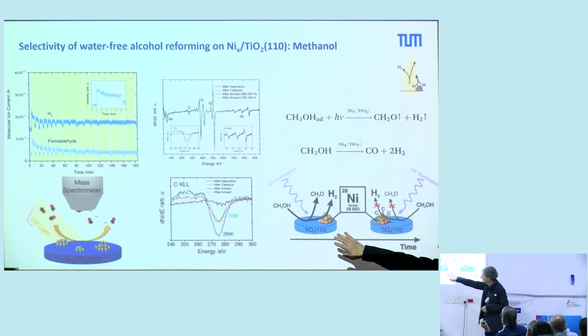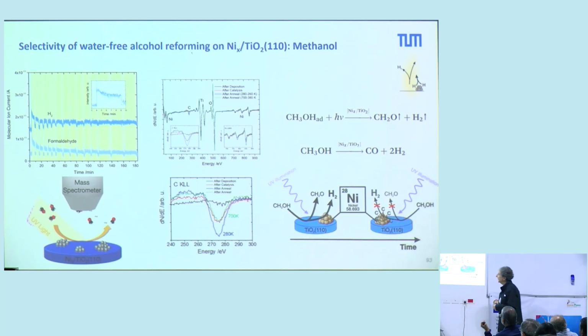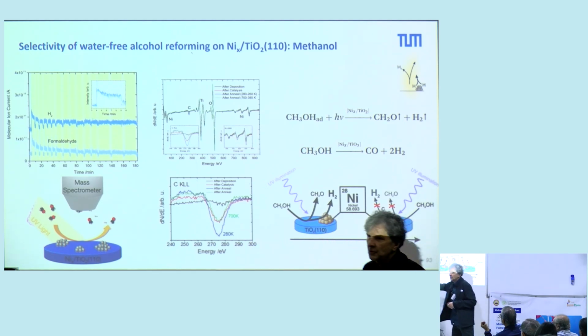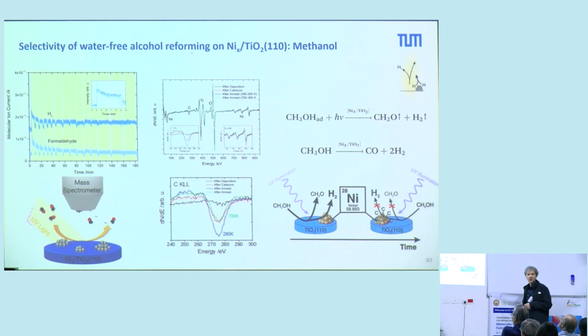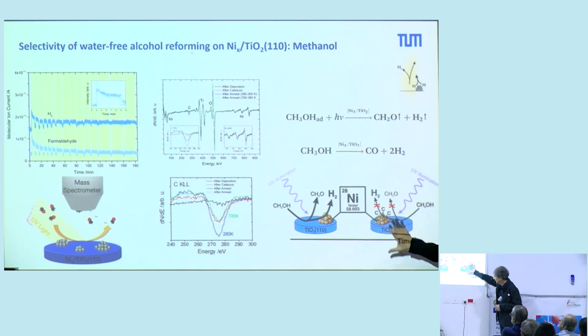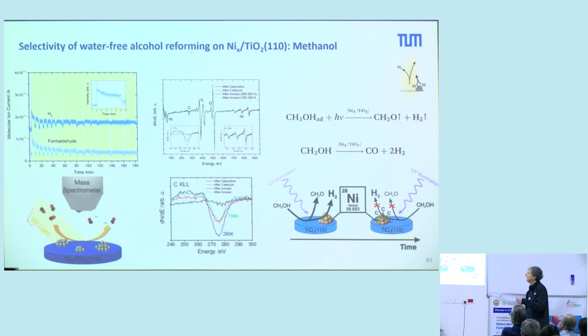This has also been observed by Auger spectroscopy, where we see clear evidence that we produce this carbon layer on these nickel clusters. That means it is important that you somehow design your co-catalyst so that it is not poisoning.